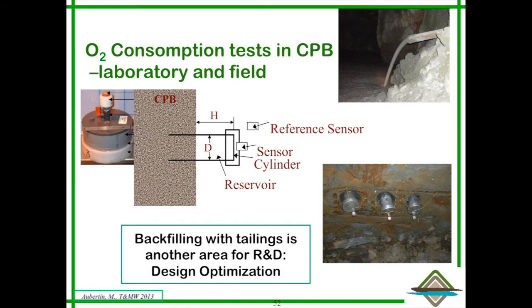I mentioned that you can return your reactive tailings underground. Of course, you may be worried of having some oxidation underground. So this has been tested. These are tests conducted at a mine in Abitibi where you have cemented paste backfill made with reactive tailings. What we did is we measured both in the lab and in the field the oxidation, the depletion of oxygen in these modified oxygen cells.